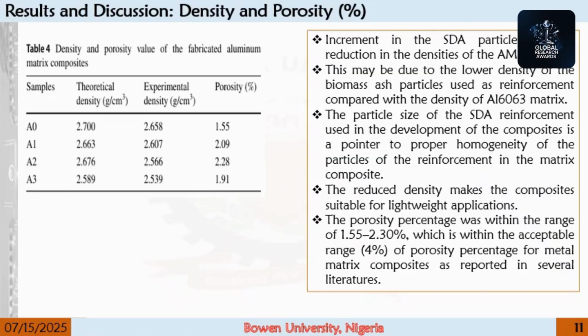Now, for the density and porosity, Table 4 shows the theoretical density and the experimental density. The theoretical density was determined using the rule of mixtures, while the experimental density was determined using mass over volume, and these are the results obtained. And porosity was calculated by subtracting and taking it over the theoretical density to determine the porosity value.